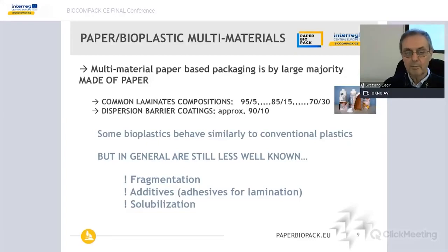Generally speaking, some bioplastics behave very similarly to conventional plastic. This is the case, for example, of bio-based polyethylene. Bio-based polyethylene is basically the same polymer as the traditional polyethylene, and the behavior in the paper recycling process is exactly the same. Nevertheless, not all bioplastics are well known, and sometimes we can get into some issues like fragmentation, or adhesives for lamination that are different from the ones normally used for traditional plastic lamination, and also in some instances an excessive solubilization of the barrier in the process water.